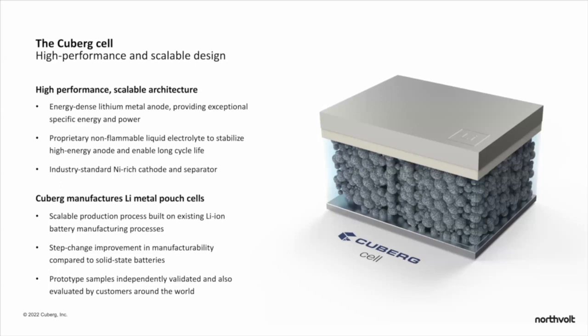Other than the electrolyte and the lithium metal, the rest of our cell is actually quite standard. We use a standard polyolefin lithium ion separator, as well as a standard nickel-rich NMC cathode material, essentially the same cathode material that Northvolt already uses today in their automotive products. And so you can see it really does leverage to a substantial extent the supply chain and the maturity of a company like Northvolt, but really focused on making innovations where it really matters on the lithium metal anode and on the liquid electrolyte.